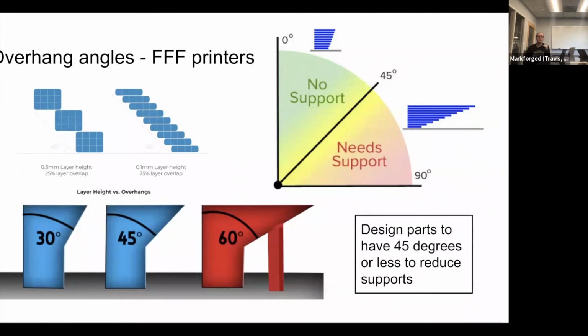However, when you go to those lower layer heights, say 100 micron, 50 micron, you're able to kind of stack those up better in such a way that they're supported by the layer below it. So you can actually get overhangs that are a little bit steeper, maybe up to 50 or 60 degrees. This will also vary widely on the material that you're using. So like PLA is very good at bridging and cooling almost immediately. We have other materials that droop and tend to be more viscous or less viscous when printing. Next.